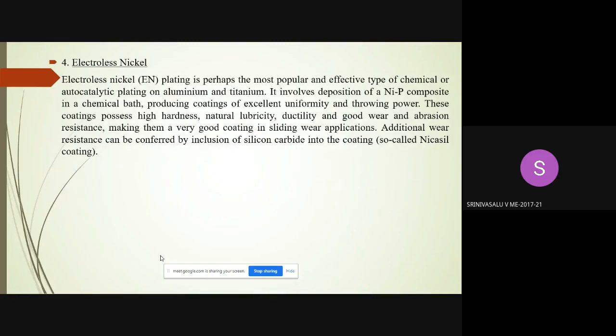Then the last method is electroless nickel. Electroless nickel plating is perhaps the most popular and effective type of chemical or autocatalytic plating on aluminum and titanium. It involves a deposition of nickel phosphorus composites in a chemical bath, producing a coating of excellent uniformity and throwing power. These coatings possess high hardness, natural lubricity, ductility, and good wear and abrasion resistance, making them very good for sliding wear applications. Additional wear resistance can be conferred by inclusion of silicon carbide into the coating.